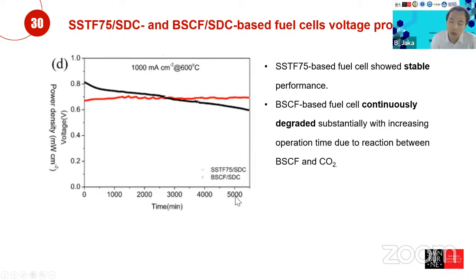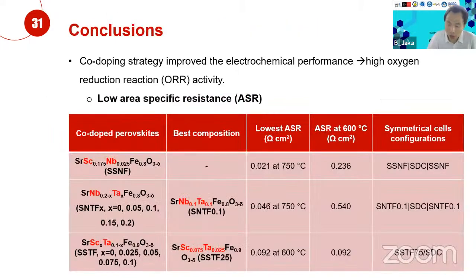When we increase the time up to 5,000 minutes and compare the BSCF with the SSTF, we see that the BSCF decreases, but the SSTF performance, although it fluctuates a little bit, maintains a much more stable performance. The instability in the BSCF case is caused by the reactions between the BSCF and the CO2.